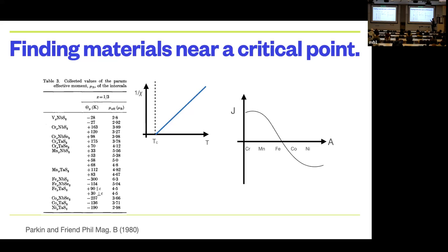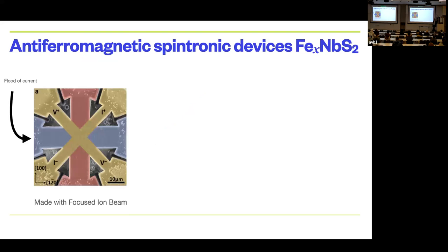So I decided to study these iron compounds, which as you can see kind of vary between positive and negative, hoping that they might be close to some kind of critical point that I could use in exactly the kind of technology that was being studied for these antiferromagnets. So that's how we came across these materials. Okay, so we took one of those single crystals. We used a focused ion beam to machine these 8 contact devices, this is false color.